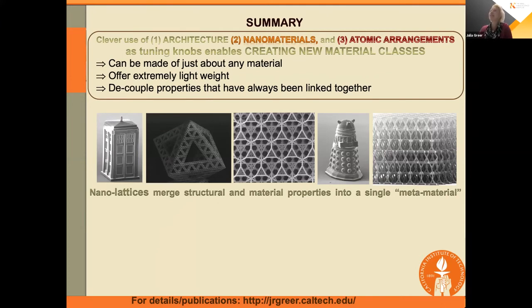And I think the key message I'd like to leave with is this. If you are clever about three particular aspects of material design, one of them, of course, is the specific architecture that you're prescribing. What kind of architecture are you interested in? Is it periodic? Is it aperiodic? Is it a nanoTARDIS? What is it that you're really after? The second one that's very important is the nanomaterials and their response to the size effect. Every material has some kind of a size effect associated with it, but it's not uncoupled from its microstructure. And that's the third knob here, which is the atomic arrangements. And it's very different depending on this combination of the external dimensions and the underlying atomic level microstructure. Once you understand these three very critical parameters, you're able to create materials with entirely uncoupled properties, combinations of properties, and attaining entirely new white space within material design.